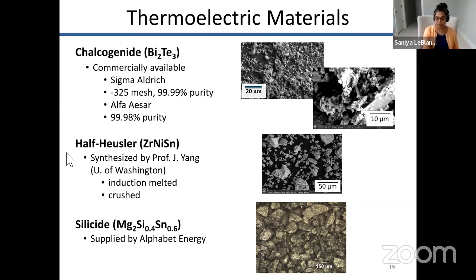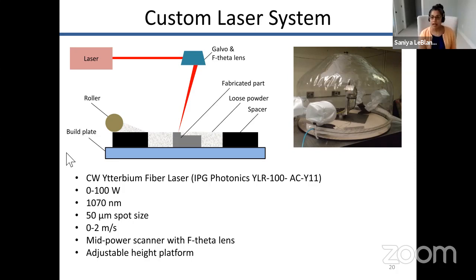And because we were working with really novel materials, what we ended up having to do is build our own laser additive manufacturing system. So in our lab, we've built our own custom laser additive manufacturing system that has a continuous wave laser, variable power up to 100 watts. And just like a commercial system, it has a scanning system that allows us to scan the laser across a powder bed underneath it. And all of this is inside of a flexible laser welding enclosure that actually allows us to do our processing in an inert gas environment.